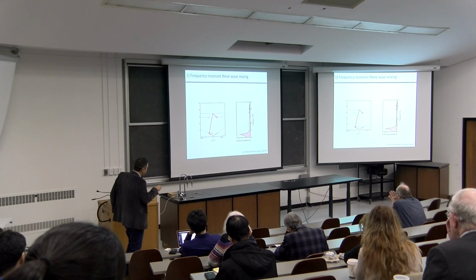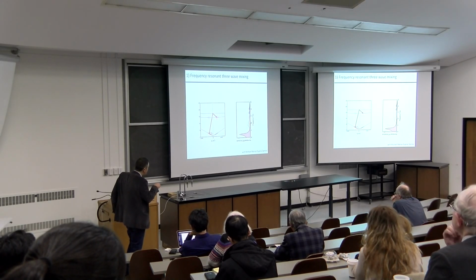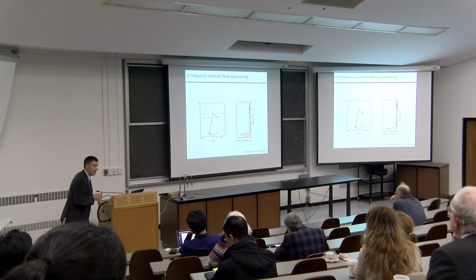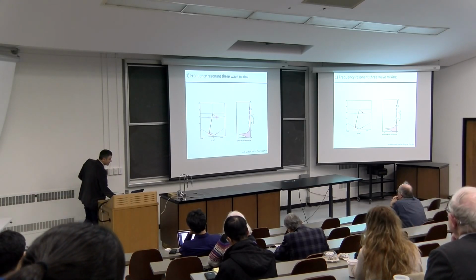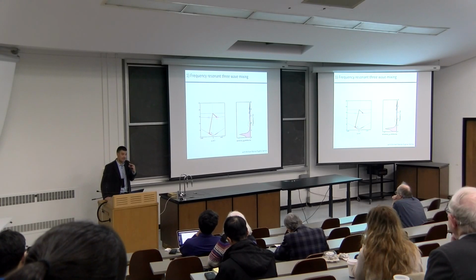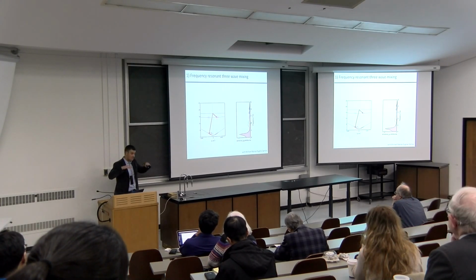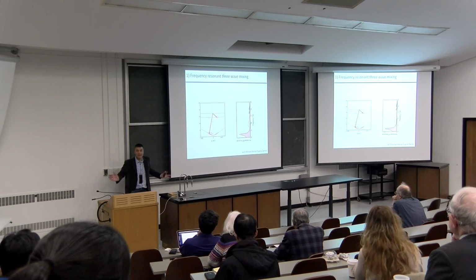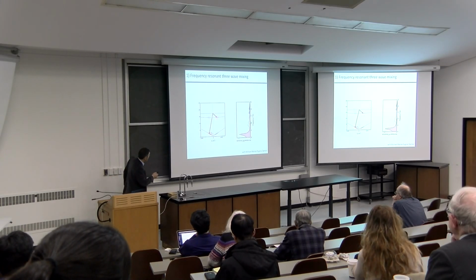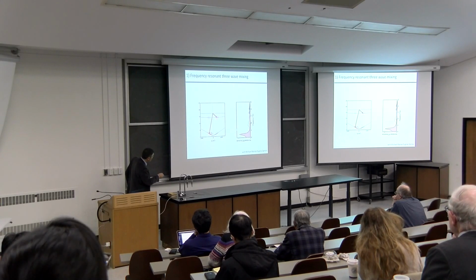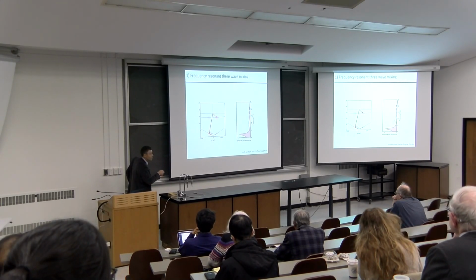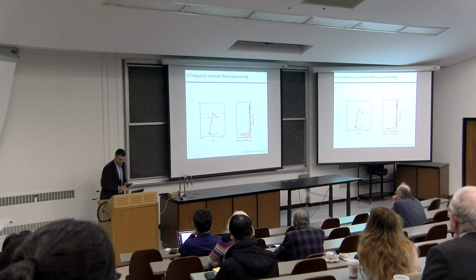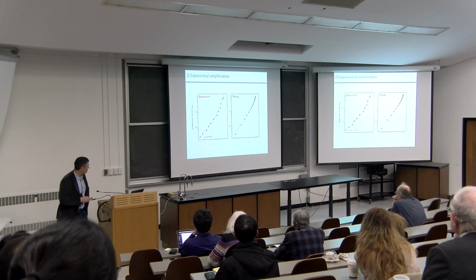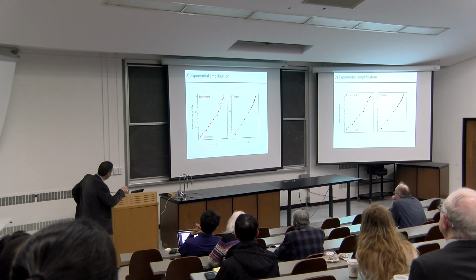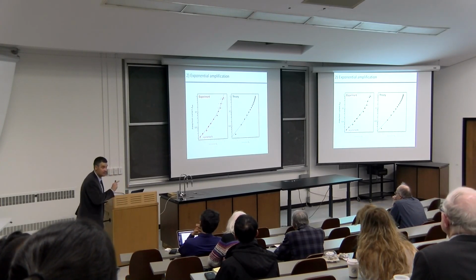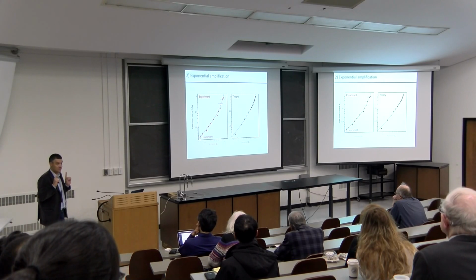I can see that my plasma mode is being generated at a frequency which is commensurate with the generation at that momentum. And again, the second prediction was that this is a parametric process, which means that I am taking fluctuations of the superconducting order in the superconducting state and I'm amplifying them. Okay? So now, because I can measure this phonon and this, I can plot this as a function of this. These are two measured quantities. And so what I find is over 3 orders of magnitude, this Josephson current is being amplified exponentially, as I was expecting for a parametric process of this nature.